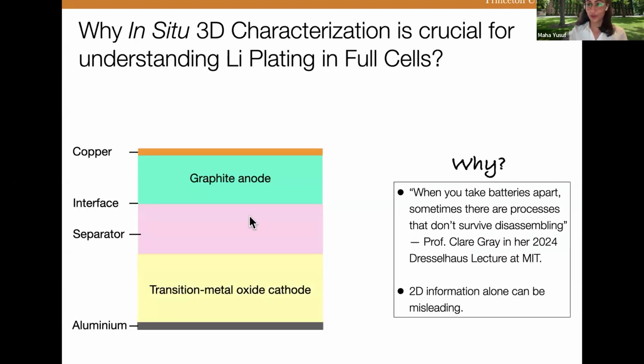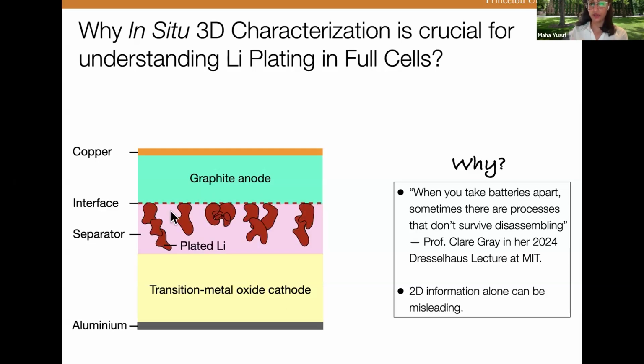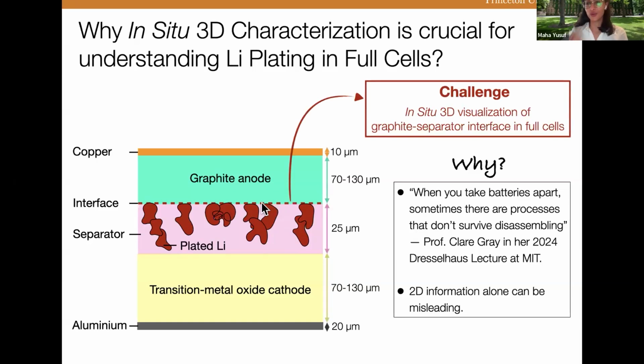Now, let's look at the schematic of the battery one more time. We have current collectors here, graphite anode, transition metal oxide cathode, separator, and this is the interface where lithium is hypothesized to start plating and grow in the form of these deposits, then poke holes through the separator and result in battery short circuit. Now, investigating lithium plating or this lithium deposition in 3D in situ is so difficult because visualizing this interface in situ in 3D in a full cell battery, especially at these relevant micron length scales, is extremely challenging in itself. Now, my approach to address this challenge uses in situ 3D neutron and X-ray imaging modalities.